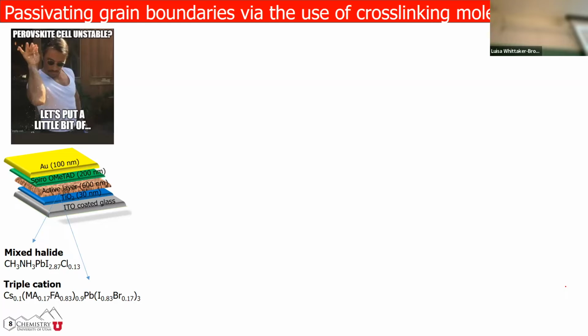Okay, so the thing is, with perovskites, every other week they start changing the composition because certain compositions give you the highest efficiency. So we started playing with these compositions, and I'm like, this is just nonsense. So we actually stayed with two different compositions here. The mixed halide, where we have the iodide and the chloride, and then the triple cation that basically has every other cation that you can find under the sun. So yeah, I basically call that the soup.